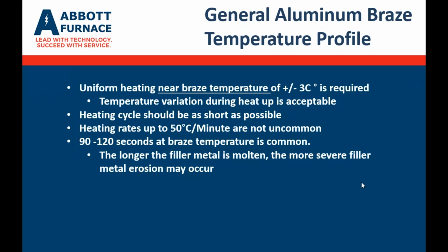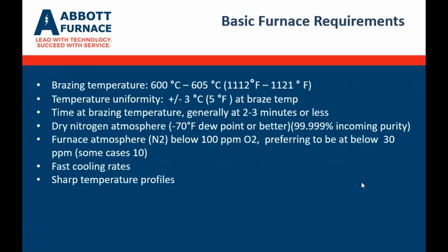The longer the filler metal is molten, the more severe filler metal erosion may occur. So just to put it in there for 5 minutes at temperature wouldn't be good either, because you're going to create a lot of problems as well. So it is a very short time. You get in, you get up to temperature as quickly as possible, go through your required time at braze temperature, and then cool down as quickly as possible.